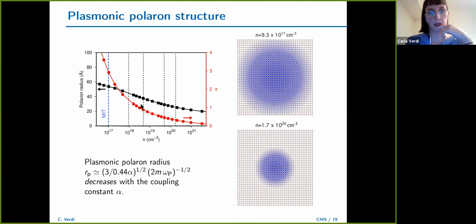So here in red, it's the estimation of alpha, which is the coupling strength with respect to doping. So you see it decreases as expected. But also the polaron radius decreases with the doping. And this is kind of counterintuitive because for a standard phonon polaron, you would expect that when the coupling decreases, the polaron radius becomes larger. Instead here, the polaron radius becomes smaller, and that is due to the strong density dependence of the plasma energy. So this is nice, but we weren't fully satisfied with it because, as I said, we had to use a model, and with our perturbation theory tools, we could not really describe the electron localization.